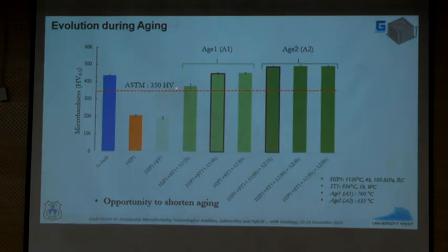The first step of aging, 1 hour, 4 hours, 8 hours, and then the second step of aging, 1 hour, 4 hours and 8 hours. Our argument then was that you've already accomplished what you needed, so not much difference there. So, can we stop this after 4 hours?